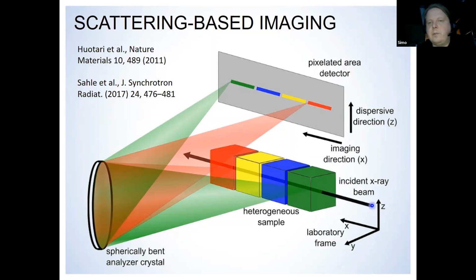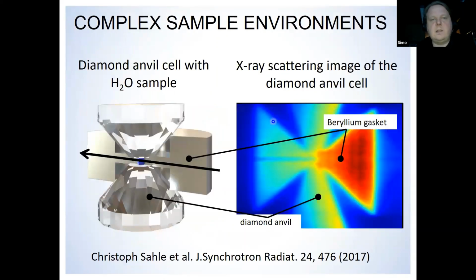So if your beam is a pencil beam focused in both directions, then the one dimension that it's penetrating through the sample will get imaged onto the detector. Basically, this imaging comes for free, because if you placed a zero-dimensional point detector here, you would just integrate over all these regions, and this doesn't come at the cost of intensity, for example. So it works quite nicely in these complex environments, where we can now get rid of the scattering contribution from other parts of the setup than the sample that we want.